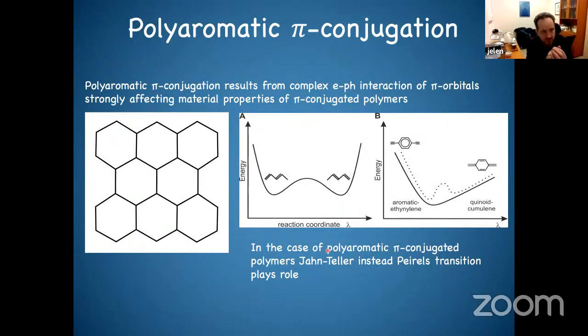Again, you can look at these polyaromatic conjugated polymers as a combination of two things. One is of course electronic correlation, but on top of that, not all the bonds are the same. There are also local distortions, and this gives rise to a kind of vibronic effect. So what you see here is a very complex system, with an interplay between electronic correlation and vibronic correlation. That is why it is such a complex system. And I will talk in a minute about these Jahn-Teller distortions or the Peierls transition.